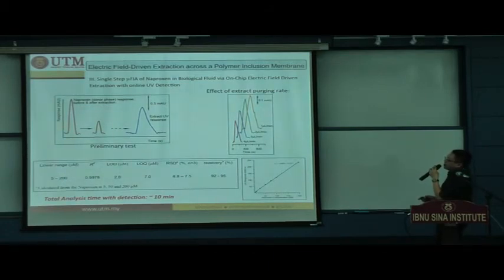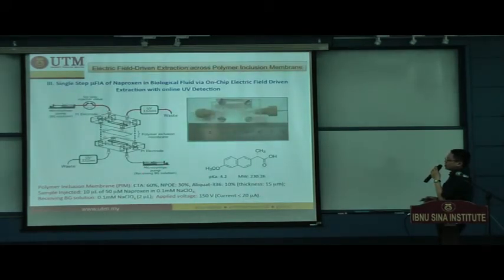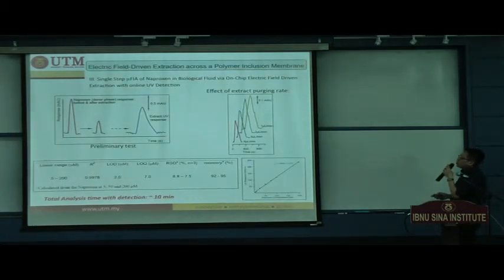Look at detector number 1 here. The amount of naproxen in the beginning, without turning on the voltage, gives a sensitivity of this height. But once you turn on the extraction voltage, the peak for naproxen reduced quite a lot, which means a big portion of naproxen has already migrated into the membrane and maybe across the membrane. On the other hand, after the extraction, we turn on the receiving background solution pump to purge the enriched analytes. We noticed that a huge naproxen signal was obtained.